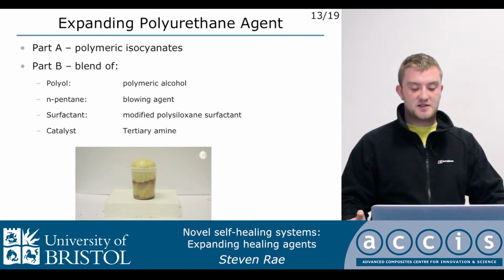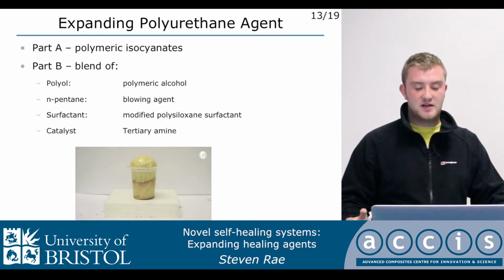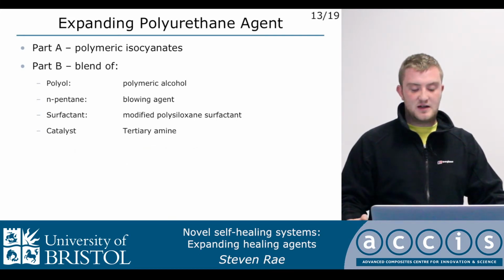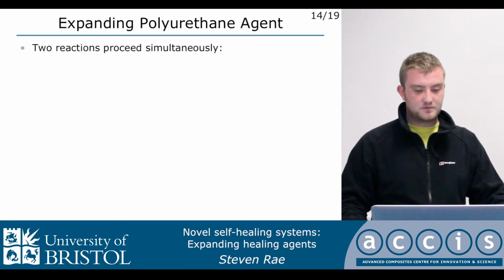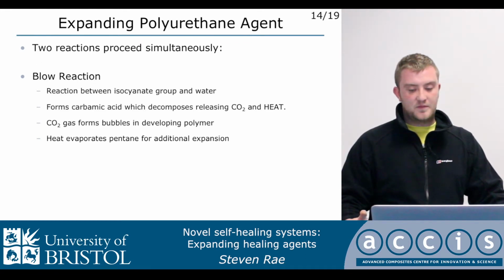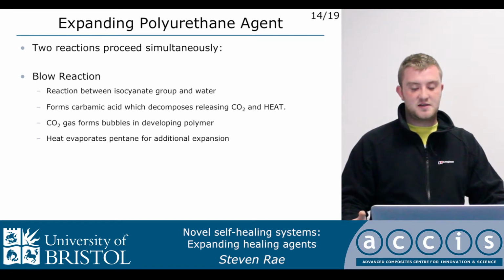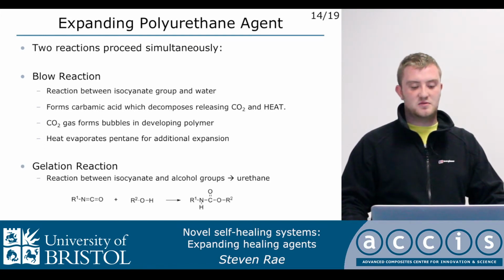This system is much more versatile in that we can alter the amount of blowing agent in there and vary the expansion. That being an example of how extreme it can be. So how does this work? Two reactions proceed at the same time. The blow reaction, where the carbamic acid which forms in the reaction decomposes, giving off carbon dioxide. This is the main blowing agent that allows the polymer to expand, but it also involves heat, and we can use that heat to evaporate a solvent that's mixed in there if we want additional expansion. And at the same time we have the gelation reaction, which is the actual polymerization reaction itself.